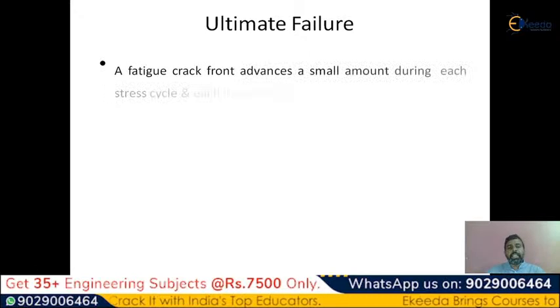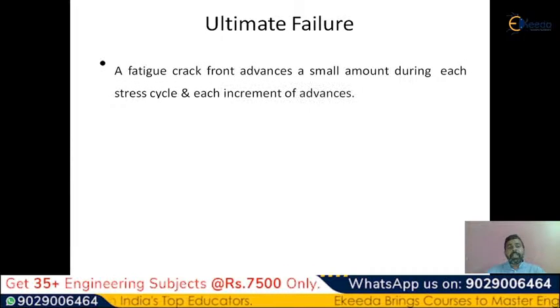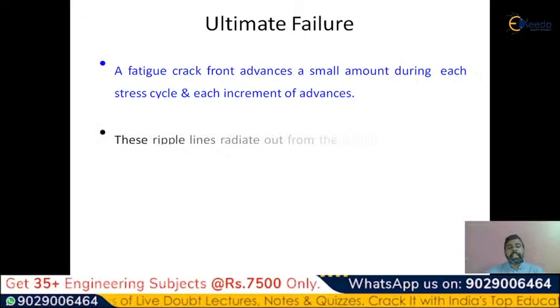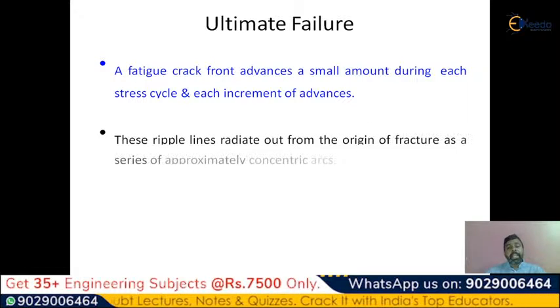Ultimate failure means in this failure mechanism, the third one, the fatigue crack front advances. That means automatically when the second stage is observed, it leads to the third stage, where the crack advances a small amount during each stress cycle. That means the crack is going to accumulate. So a small crack is started and it grows and accumulates, and in each increment of advance, automatically the crack is going to become bigger and bigger.